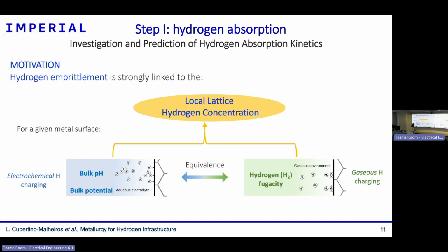So the equivalence in that case would be the bulk pH and potential producing a certain hydrogen pressure at the surface of the metal. That would be equivalent to that case. In a sense, the equivalent is: what are the electrochemical charging parameters that would result in the same absorbed concentration as if my metal was exposed to a hydrogen pressure instead of an aqueous electrolyte?